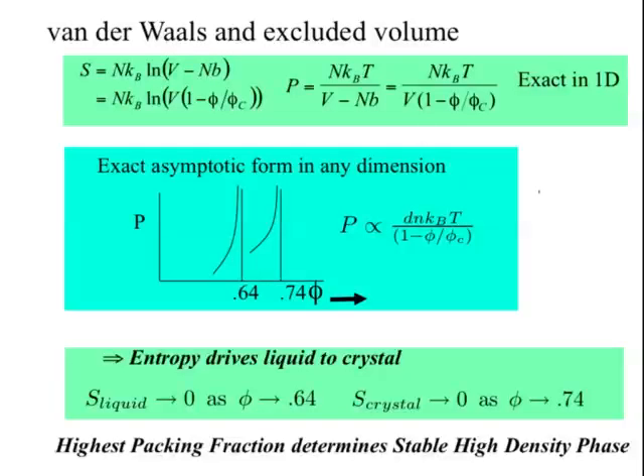And if they don't interpenetrate, then what you'd normally write down for the entropy of a system, if there's no potential, you're only concerned with the entropy would be log V. He says from V, I have to subtract the volume of each ball times the number of balls. And if I do that, the entropy now reads log V times 1 minus phi over phi C. Phi C is the concentration, the volume fraction, at which you can no longer add anything. So phi C is 74% if you make a crystal, and it's 64% if you make something that's disordered, right? And the pressure, of course, is just the volume derivative of the entropy. So pressure diverges at 74% if you have a crystal. If it's disordered, it diverges at 64%.